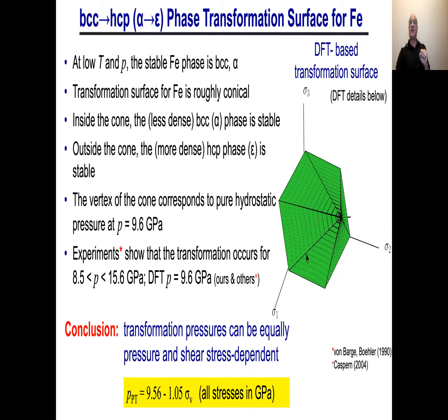And if I look at this a little bit more carefully, at the minimum transformation pressure as a function of shear stress, where the shear stress means going out radially. So if I start on this pressure axis, I go out radially along the deviatoric plane until I hit the yield surface, and I find this relationship here. Now, the thing I want to point out to you is these are all in GPa, but the thing to note here is this coefficient from DFT is about 1, which is to say that the hydrostatic stress and the shear stress are equally important in the phase transformations, okay, because the coefficient is 1. Okay, so that's an important conclusion.